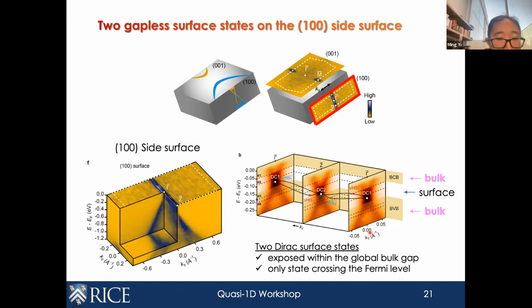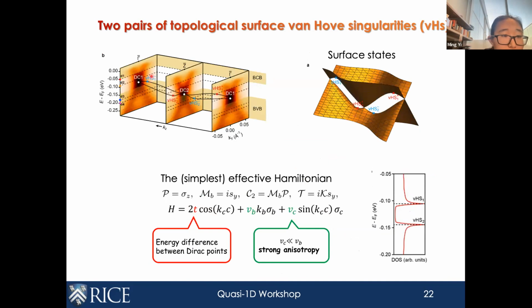So given this measurement, and also they live quite close to the Fermi level, you can imagine they will be susceptible to doping to bring them to the Fermi level. So given the experimentally observed location of these Dirac crossings, we can then work with Fan's group to work out the minimal, simplest effective Hamiltonian that respects the symmetries of the system to come up with this prescription of the surface state.